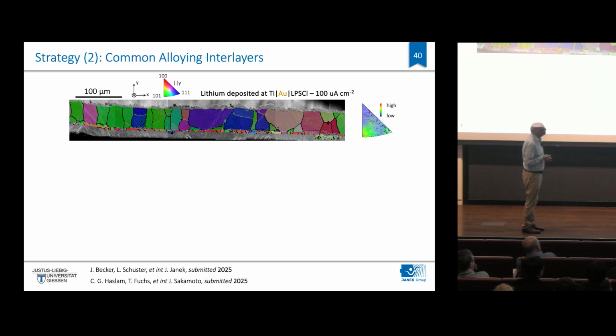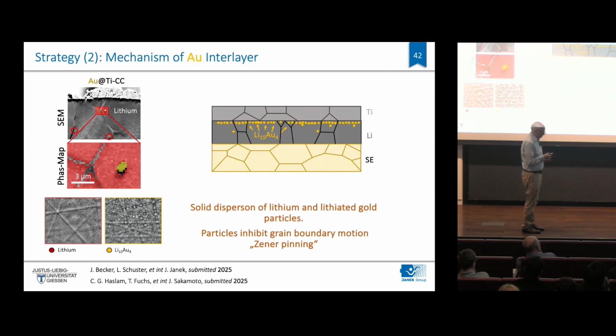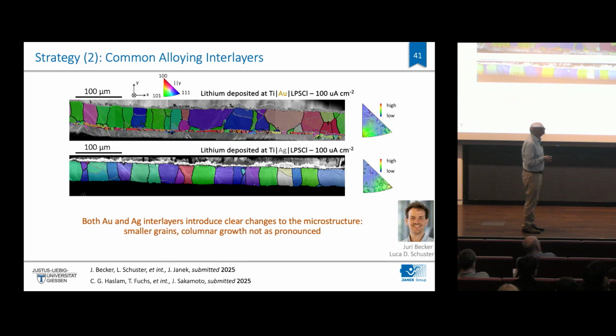So you get already a few grain boundaries that are horizontal, and also if you use silver, for example, the grains tend to be smaller. It's not sensational, but there is an effect that is statistically significant. So metal interlayers introduce clear changes to the microstructure, and we get smaller grains. Columnar growth is not as pronounced, but I would say it's not yet a sensational effect.